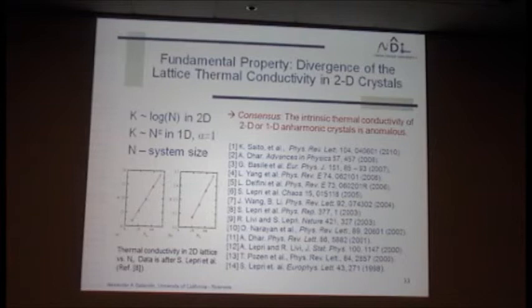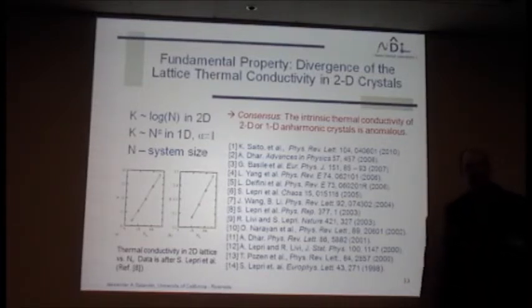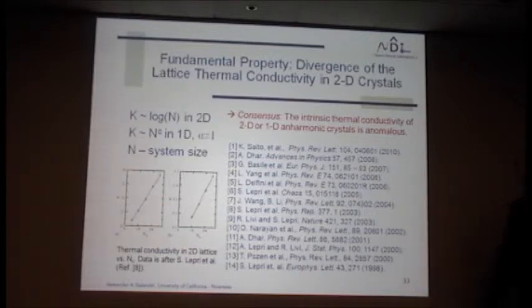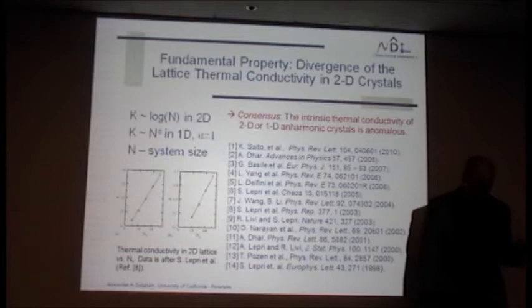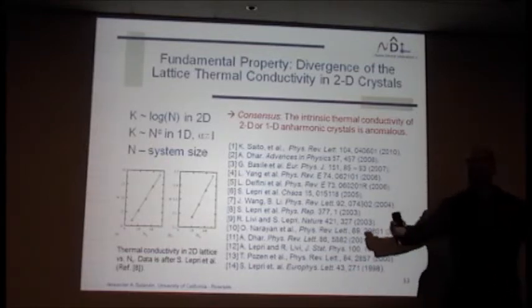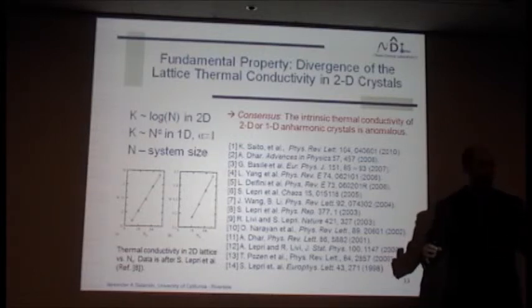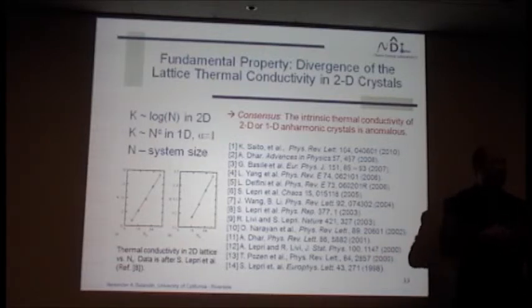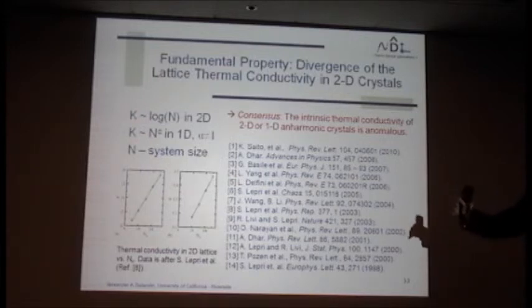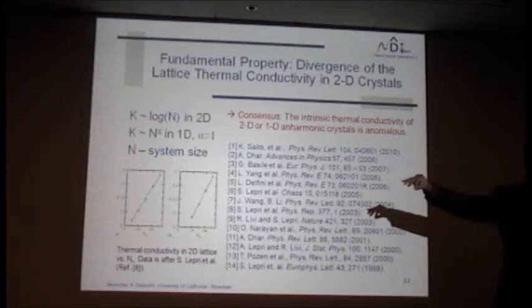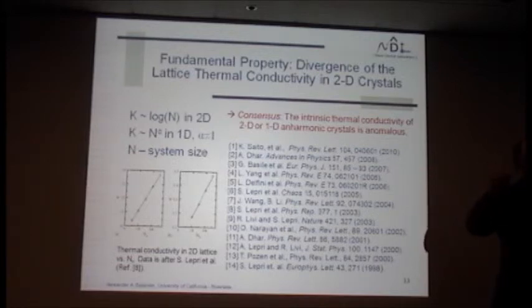There's still a puzzling question: why can you have a larger value of thermal conductivity for a two-dimensional crystal if dispersion and phonon group velocities are similar? In bulk crystals, you start with the harmonic approximation and calculate phonon dispersion. But if a three-dimensional crystal is harmonic — with no defects — thermal conductivity is infinite, because phonons do not see each other and you don't establish equilibrium. So you have to introduce anharmonicity — higher-order terms — in order to have phonons interact with each other, described by Umklapp scattering. Then you get finite thermal conductivity of a three-dimensional crystal, which scales as one over T near room temperature.